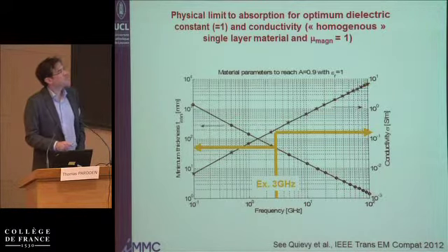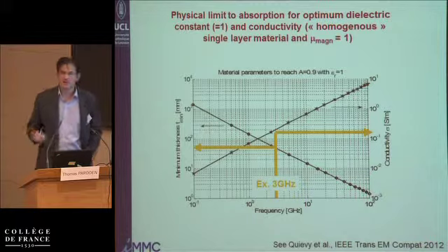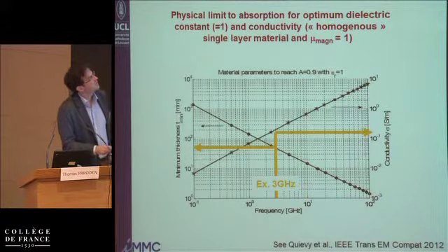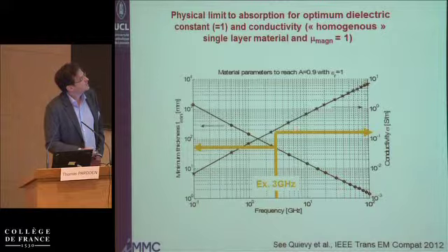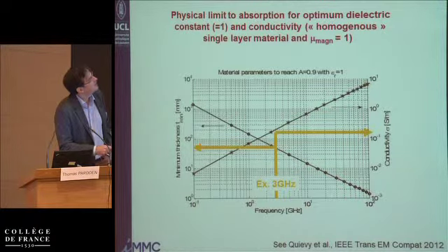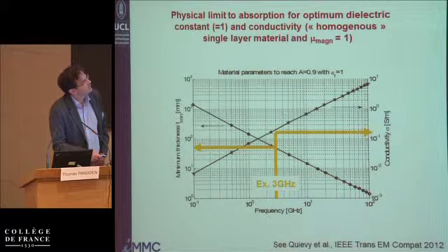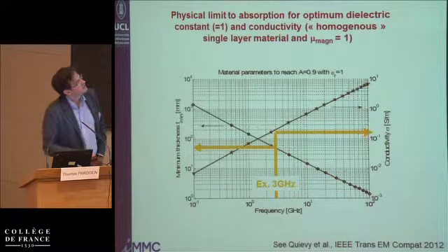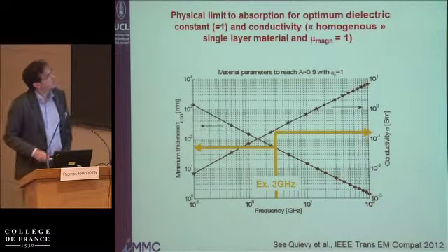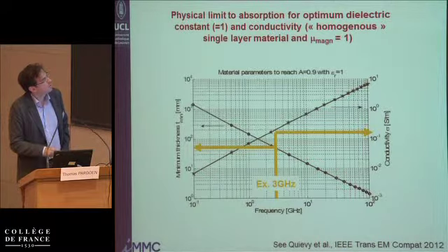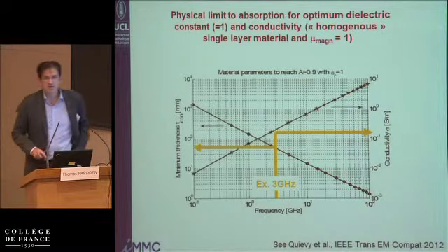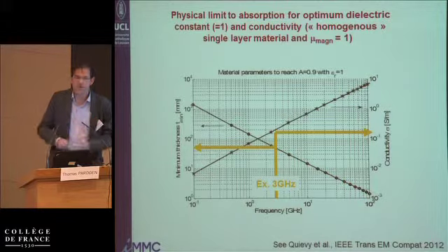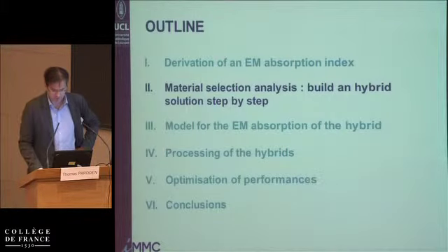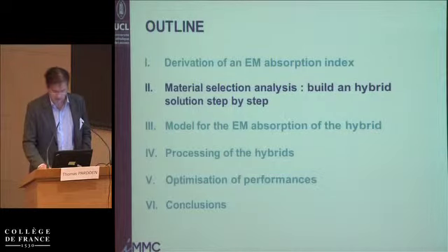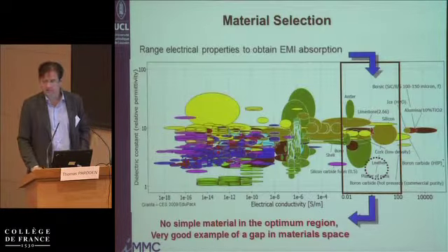So if you want to reach 90% of absorption, and say you have a material that has a dielectric constant, a permittivity close to 1, if you want to reach that, you need a thickness of here 50 millimeters, and you need a conductivity of something like 0.2 Siemens per meter. Okay, so depending on the frequency, the optimum conductivity will change. Okay, let's see how we can select a good material for that.